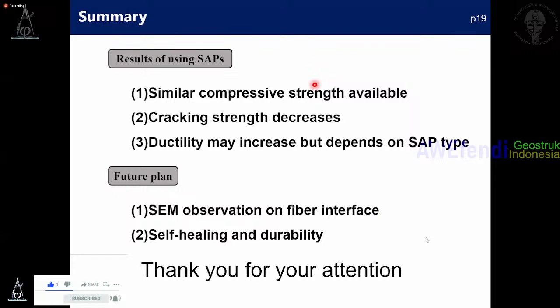Okay, so finally, I want to simply summarize. Up to our current research, if you use a SAP, sometimes you can have similar compressive strengths, particularly if you don't add additional water. But because of the initial flaws, the cracking strength decreases, but it depends on the subtype. It may enhance the fiber bonding, the interface. So finally, you may get higher ductility.